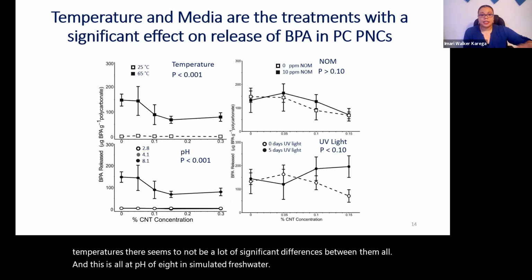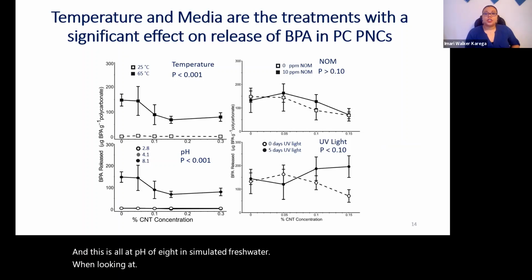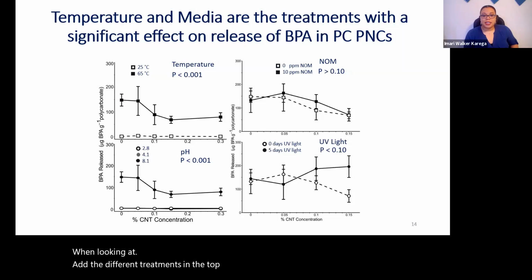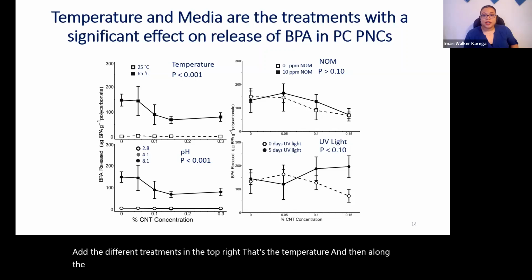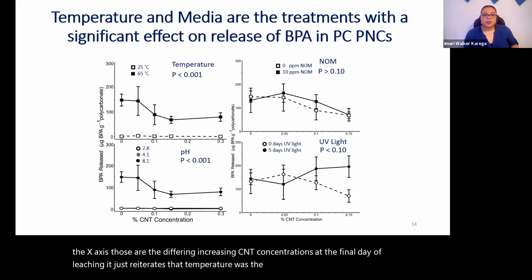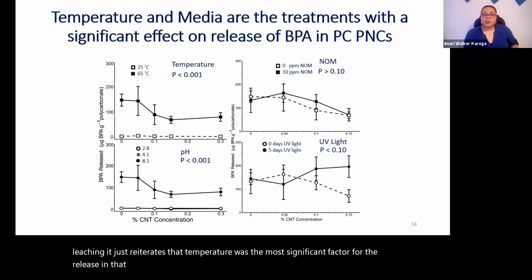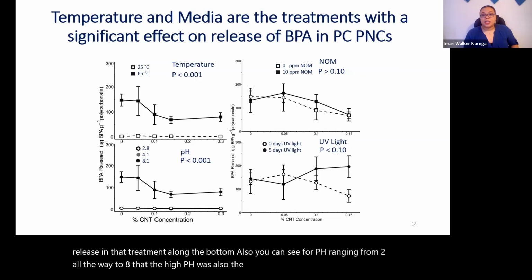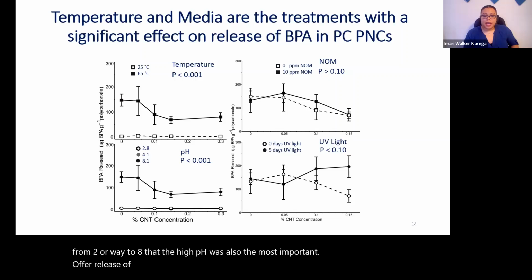When looking at the different treatments in the top right, that's just the temperature, and along the x-axis are the increasing CNT concentrations at the final day of leaching. This reiterates that temperature was the most significant factor for release in that treatment. Along the bottom, you can see for pH ranging from 2 to 8, that high pH was also the most important for release of these additives, or for bisphenol A.